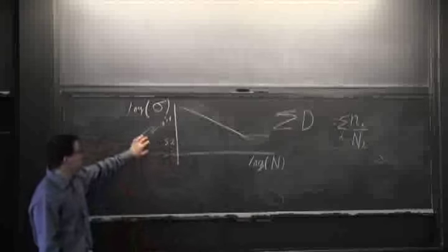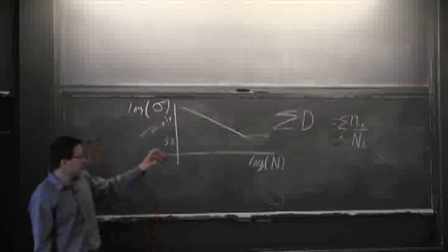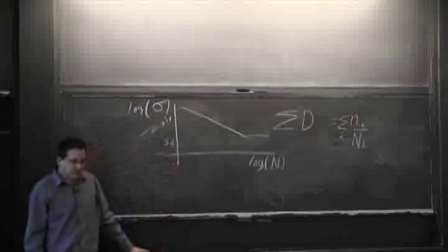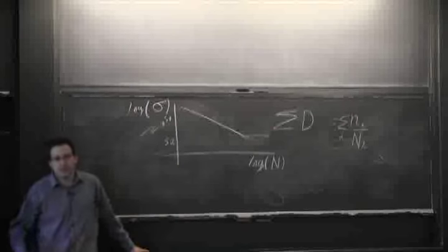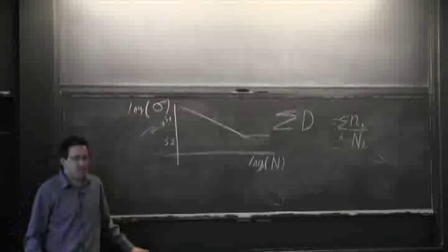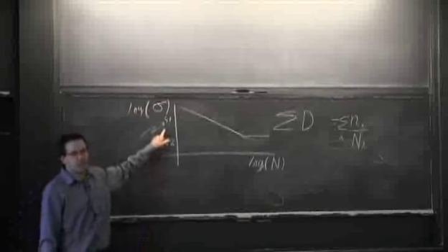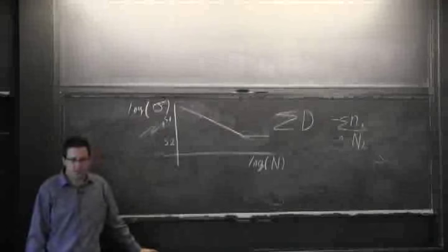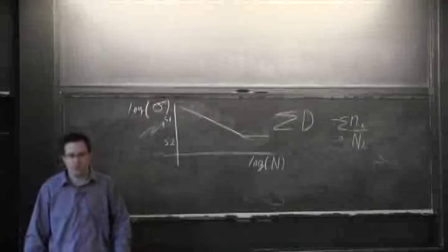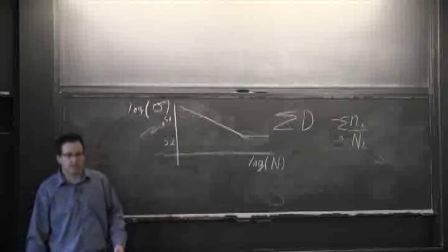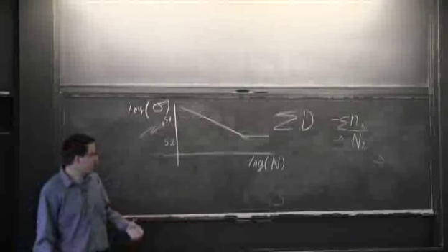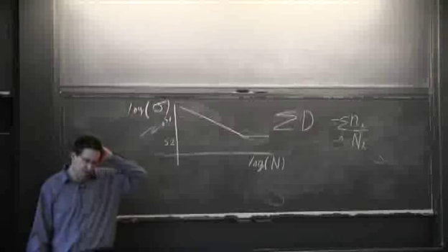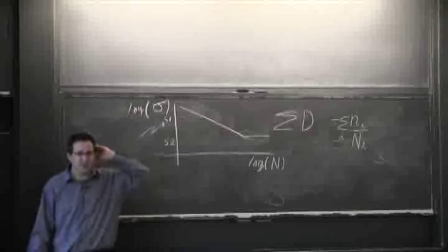So I'm not going to say to look only for the big cycles, but the big cycles sometimes end up having a bigger role than Miner's rule will say. That's why it's like any other tool. You can use it, but it may not be conservative for the high loads here. And that's really something to think about when you're looking at a specific application. A lot of times people will run full-scale tests as well, and the advantage of doing the full-scale test is you can take into account some of those rather complicated issues that are hard to calculate otherwise.